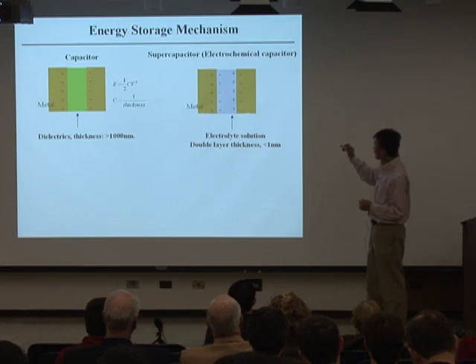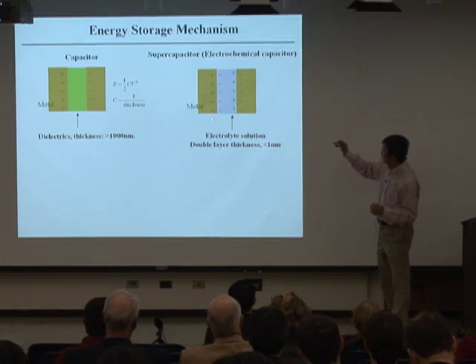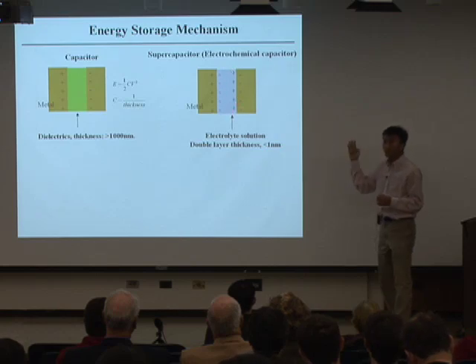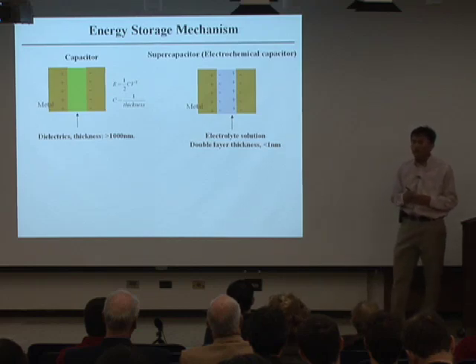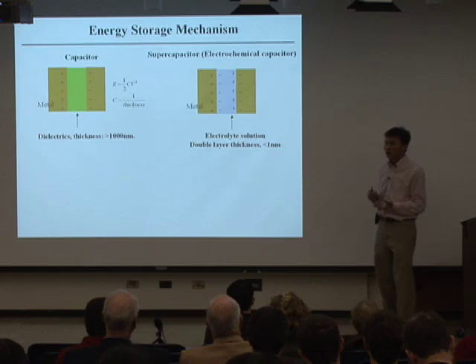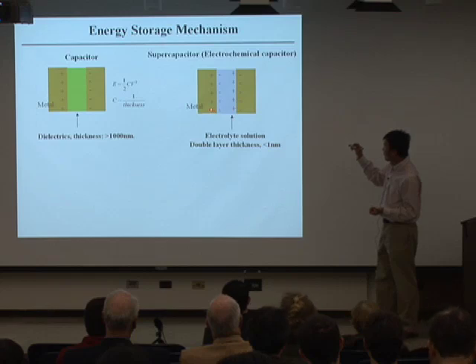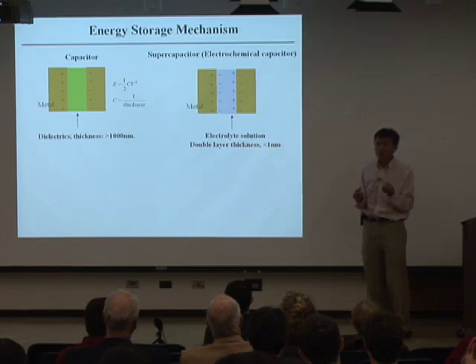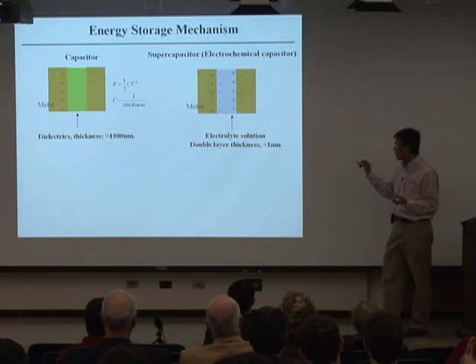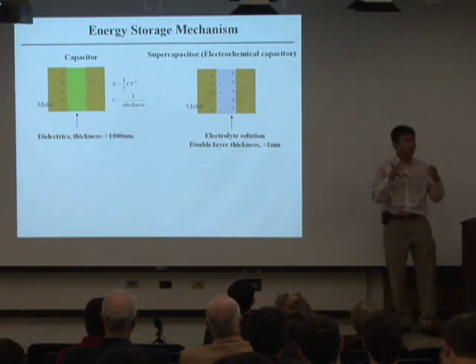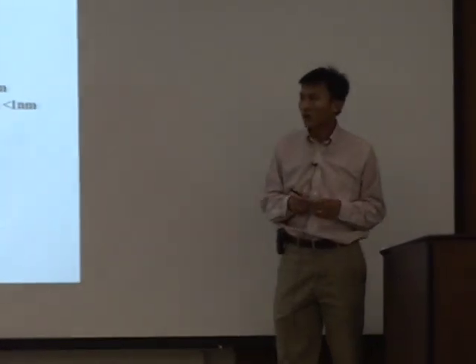If you apply a voltage, positive this side, you accumulate negative ions, that's anions, on this surface. Cations with positive charge go to the right-hand side electrode. Now the capacitance of these supercapacitors, the relevant length scale is the separation between the positive charge and negative charge. This is extremely small. The relevant thickness now is the so-called double layer thickness. With say 100 millimolar or a molar ionic concentration, this is less than a nanometer also.